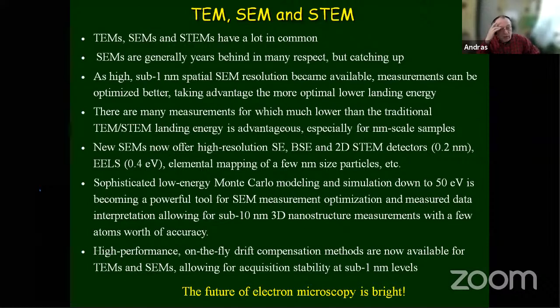So the key part is that modeling has improved. Modeling has been a part of life in TEM and STEMs for a very long time, especially for crystal and other structures, but not that much for crystal structures in SEM yet, though obviously that's also doable. But for other signal modeling down to 50 eV is becoming a very powerful tool for SEM measurement optimization and interpretation of the measured data. It allows sub 10 nanometer 3D structure measurements with a few atoms worth of accuracy, matching the results of X-ray scatterometry or TEM. So these are very, very powerful things.